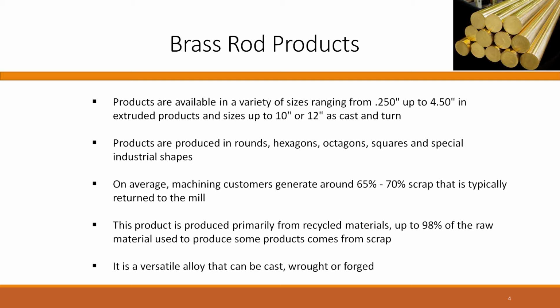Up here on the fourth bullet point, it shows that the charged material is made up of 98% scrap, and then the balance is what's needed to adjust the chemistry to whatever the ASTM specification is, or maybe a special specification on the part of the customer. So turnings, solid scrap, that's the runaround scrap from inside the producing mill gets melted, and then scrap is bought on the free market. And there's about 20 or so alloys that are compatible to the machining alloy, rod alloys that are made now.